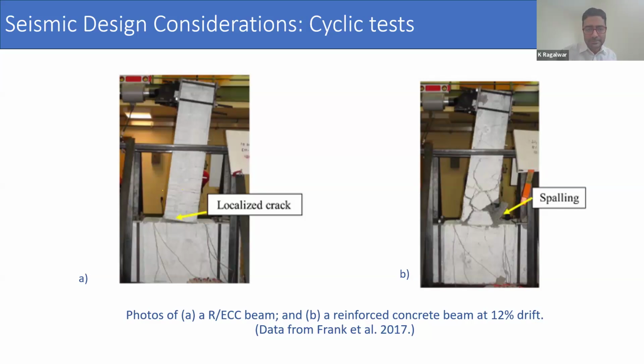And we can also talk about what happens under large displacement reversal. In HPFRCC, localized cracks can sometimes fully connect across the beams, and when that happens, shear sliding can occur along that crack plane. So imagine if cracks are reaching from one end to the other, then basically at that location it is very weak in shear, and we can see some shear occurring at that location and in the reinforcement as well.